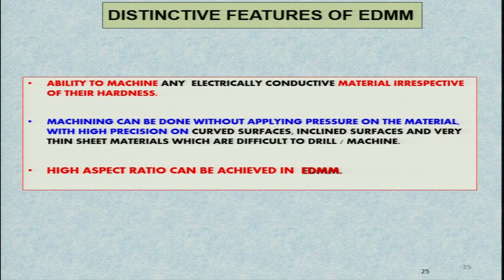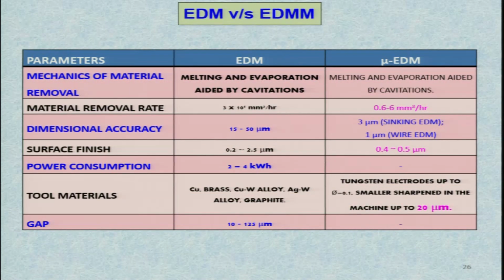Now, high aspect ratio can be achieved in electric discharge micromachining processes also, as in case of electric discharge machining. Then let us see some process variables which compare EDM and EDMM process. I will not go into detail over here, but I will just give you an idea about this. The mechanism of material removal in both the cases remains the same, whether EDM or micro EDM. Material removal rate is definitely different. It is much higher in case of EDM process, as you can see over here, 3 into 10⁵ cubic millimeter per hour, while it is 0.6 to 6 cubic millimeter per hour.